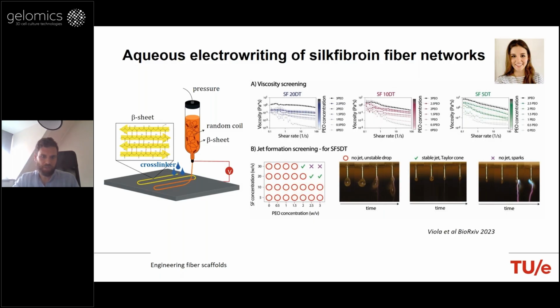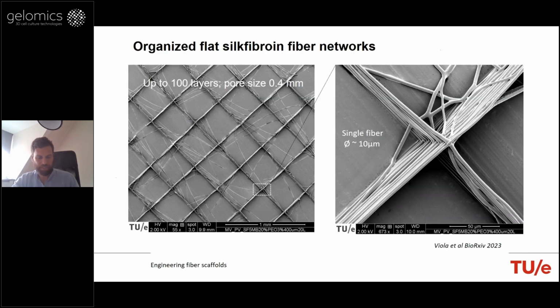And following a design of experiments, we concluded that there was an optimum in terms of the boiling time and the PEO concentration that would allow us to create a stable jet formation that was not basically dripping, and would allow us to achieve a continuous collection of the filaments. And basically this led to achieve structures, and what you see here are basically some images of the printed structures.